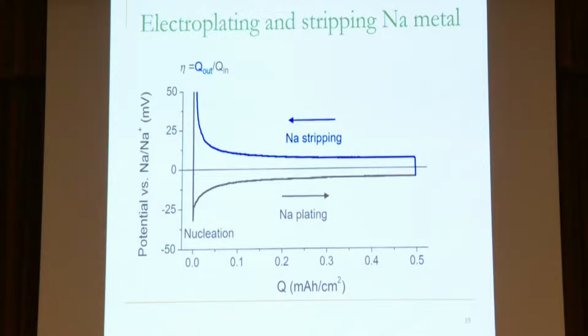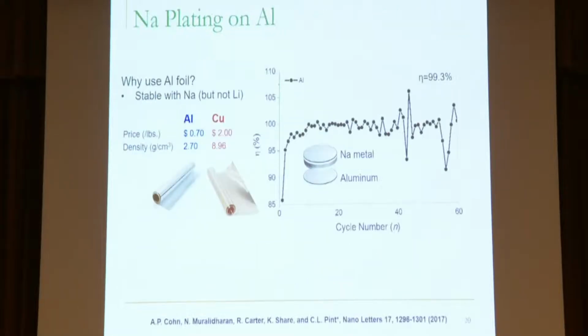A typical lithium-ion battery anode will have a charge efficiency of 99.99%, which means that you lose at most 0.01% charge every cycle. So that's our goal. So we put some batteries together just using simple aluminum. And aluminum is much better than copper for the reasons you can see here. It's cheaper and it's lighter. And we observed a coulombic efficiency, kind of jumpy, but 99.3%. Not quite what we wanted.